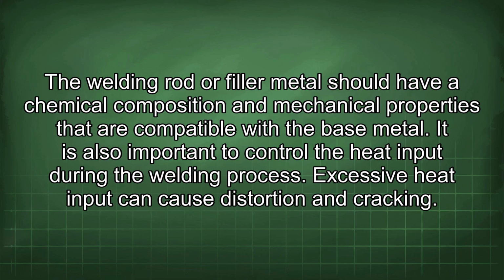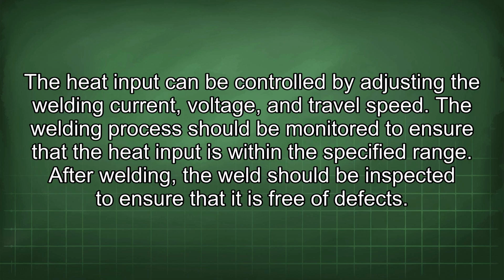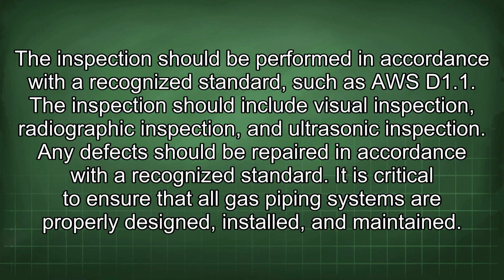Excessive heat input can cause distortion and cracking. The heat input can be controlled by adjusting the welding current, voltage, and travel speed. The welding process should be monitored to ensure that the heat input is within the specified range. After welding, the weld should be inspected to ensure that it is free of defects. The inspection should be performed in accordance with the recognized standard, such as AWS D1.1. The inspection should include visual inspection, radiographic inspection, and ultrasonic inspection. Any defects should be repaired in accordance with the recognized standard.